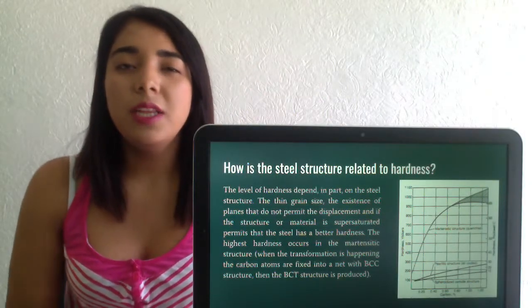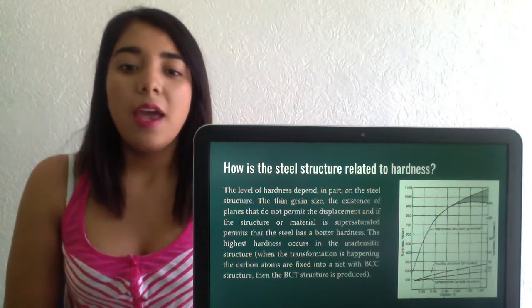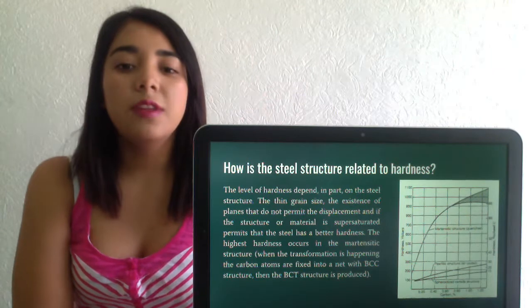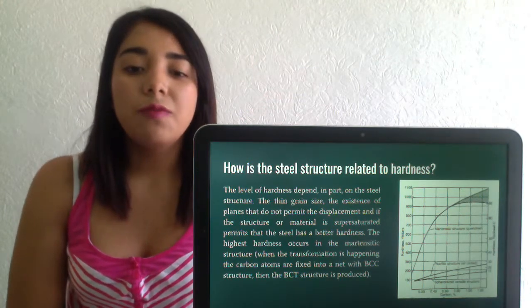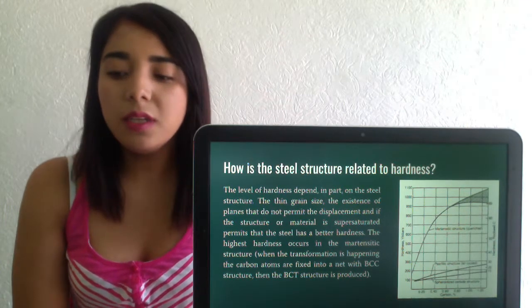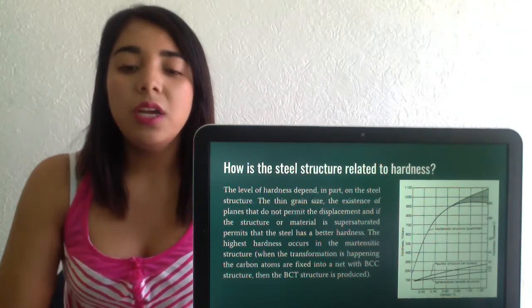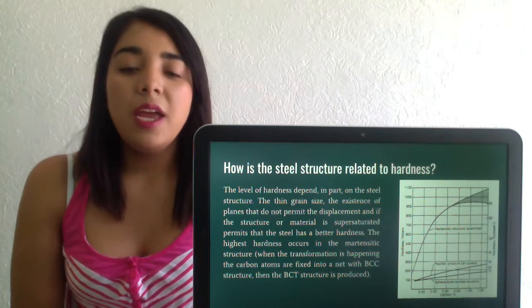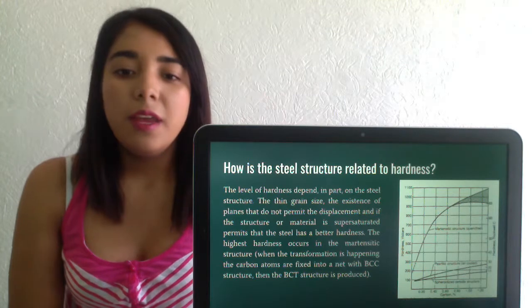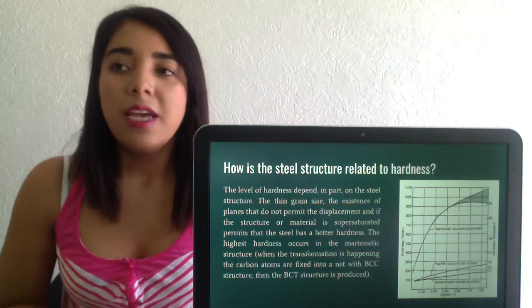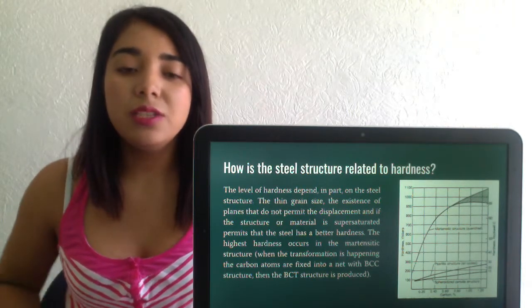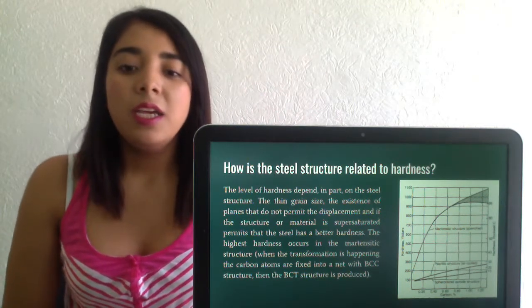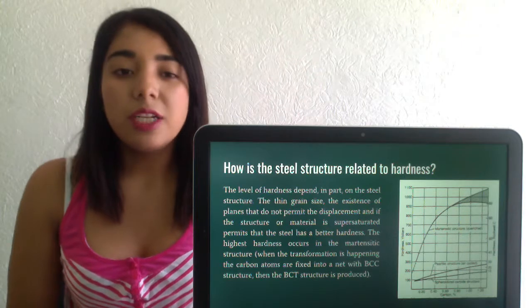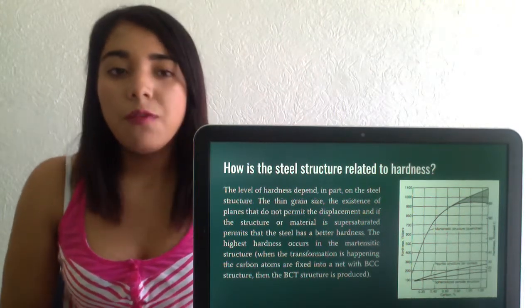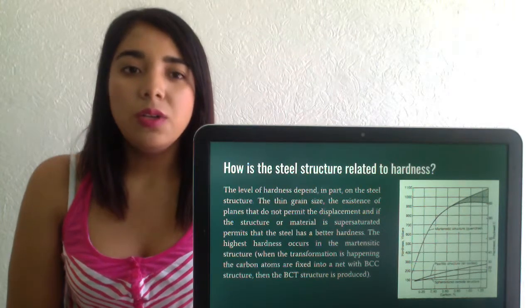The level of hardness depends in part, because there are other factors, on the structure, the fine grain size, and the existence of planes that do not permit displacement. And when the material is supersaturated, the atoms cannot move, and for this there is no displacement in the structure. The hardest structure is the martensite, that is the structure that doesn't permit the displacement, which happens with a BCC structure transformed to a BCT structure by a quench used in a heat treatment.